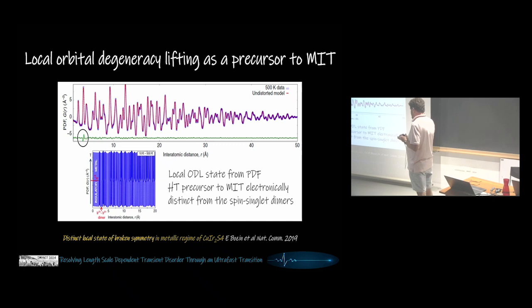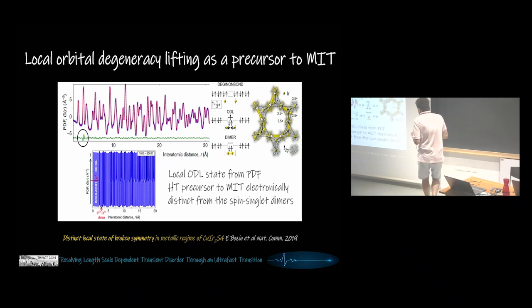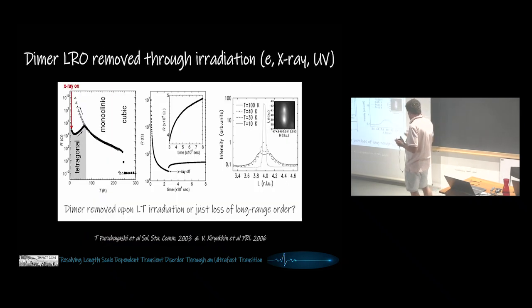And this state is distinct from the spin-singlet dimer state in that the distortion is an order of magnitude smaller. So the actual dimer peak, which is shown here, disappears upon heating. Okay. That state is electronically different from the dimer state, but I'm not going to go into that.